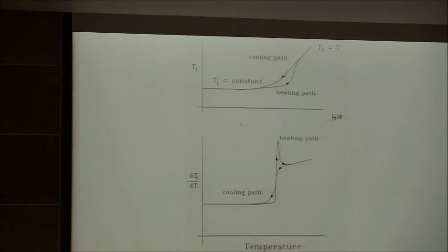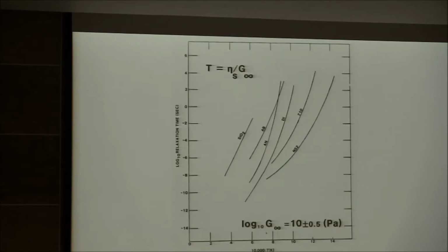So we do that. We can plot where these TGs are as a function of absolute time, relaxation time, and absolute temperature in this manner for various chemical compositions. And you see that changing the chemistry of these glasses from high silica to low silica has a huge effect on the viscosity and the relaxation. An enormous effect. So changing the chemistry of a volcanic liquid a little bit will pick it up immediately in looking at the glass transition.